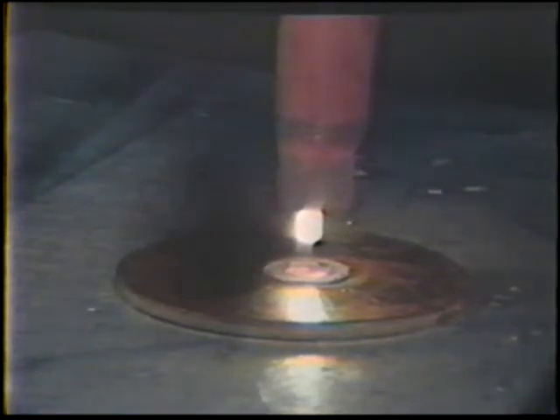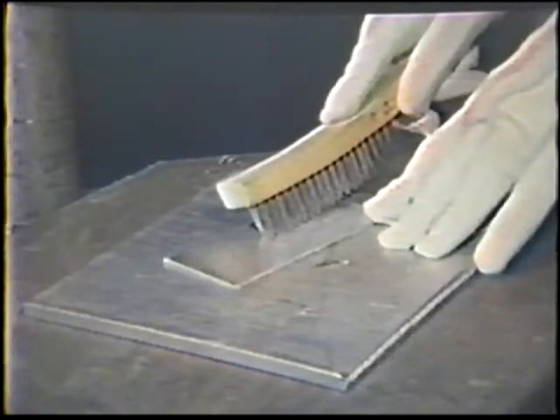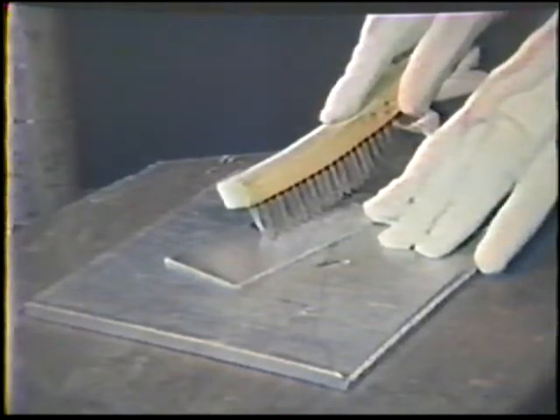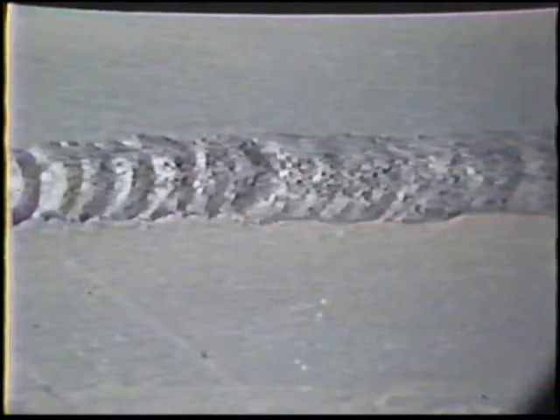Once the electrode is ready, the workpiece is prepared by thoroughly cleaning one piece of aluminum with a stainless steel wire brush to break up surface oxides. If the aluminum is not properly cleaned, heat control will be more difficult and black specks of contamination may appear in the weld metal.